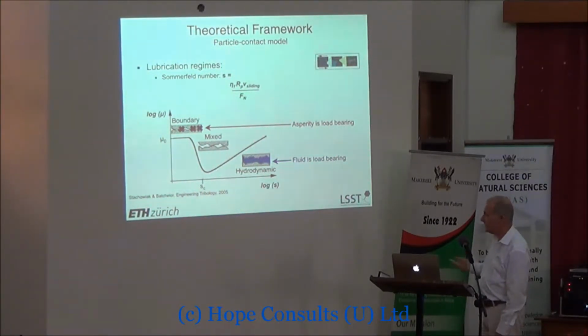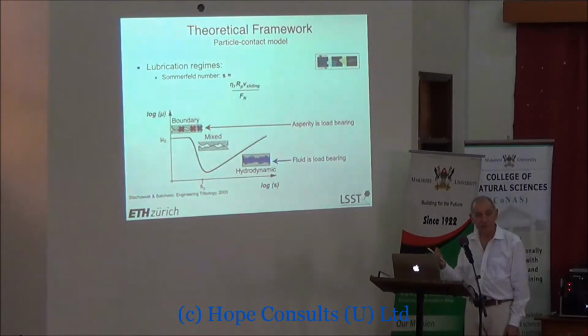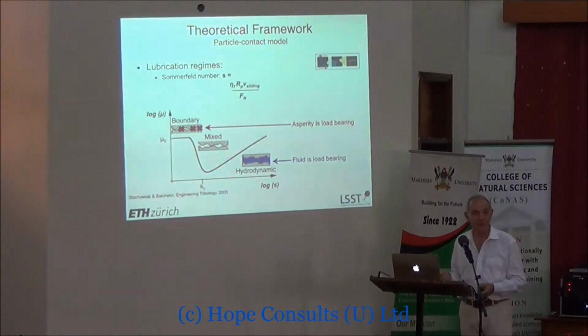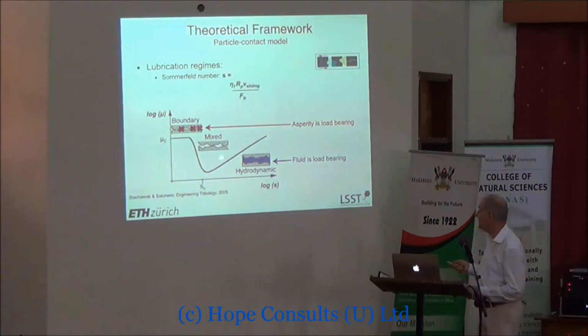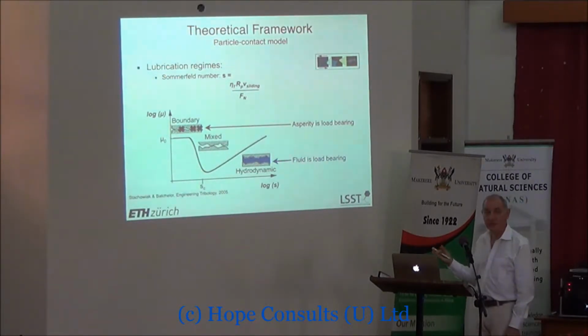Now, as you go to higher and higher speeds, then you start to get hydrodynamic lift, and the friction coefficient goes up just because of the viscosity. As things slide faster in a viscous medium, the drag goes up. That's why boats don't go infinitely fast. And so your viscosity goes up as you increase the speed. Now there's a transition between these two called the mixed regime, where part of the surface is in the boundary regime where they're touching each other, and part of the surface is in hydrodynamic regime where it's being lifted.